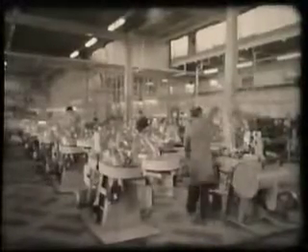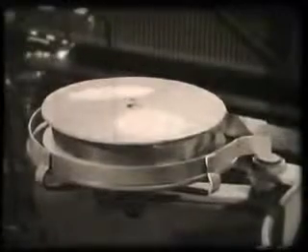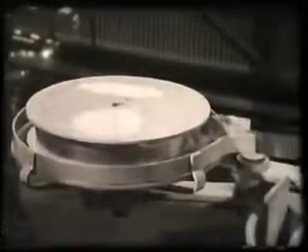On a later type of machine, the cathodes are made from flat nickel strip. These are known as lock-seam cathodes and are free from the chemical impurities sometimes introduced into the metal during the drawing of round tubing. In this scene from a research film, you can see the forming operation in slow motion.